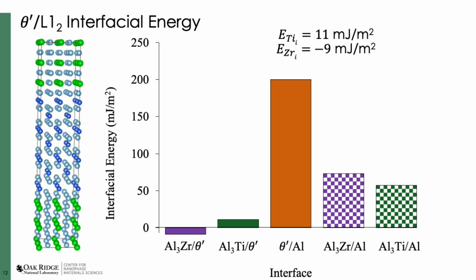Density functional theory was used to calculate the interfacial energy of this new structure and compare it to the original coherent theta prime aluminum interface. As you can see, both sides of the L12 structure have a lower interfacial energy than that of the original theta prime aluminum interface, which is widely accepted as 200 millijoules per meter squared. Remarkably, the L12 theta prime interface has an almost zero interfacial energy, while that of the L12 aluminum matrix has an interfacial energy of about 50.